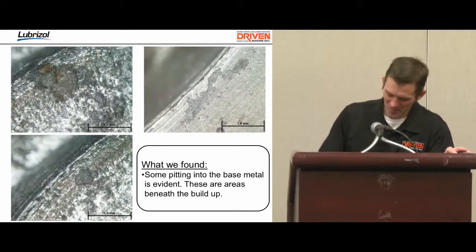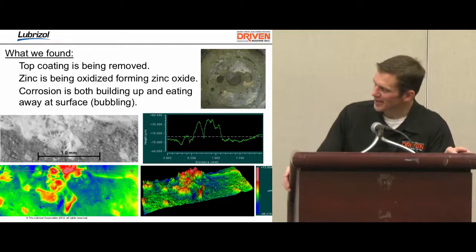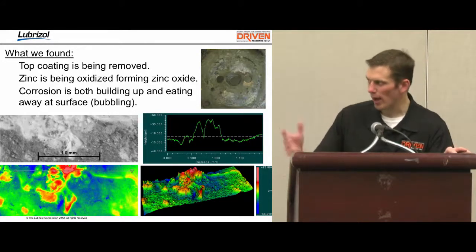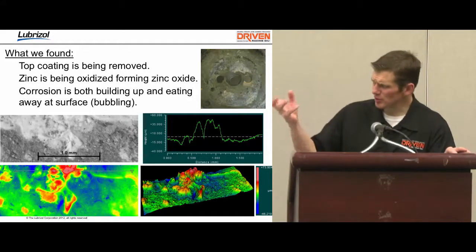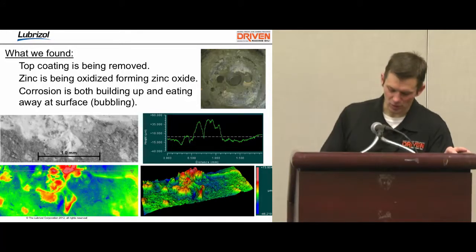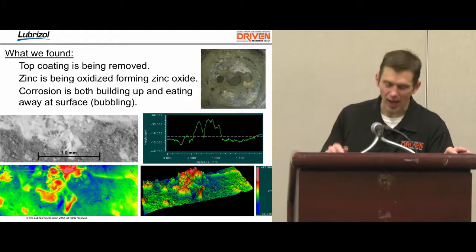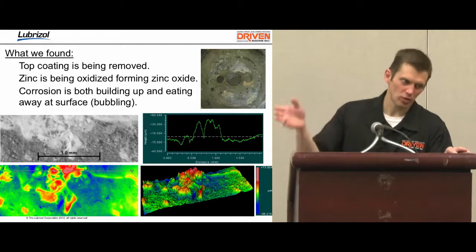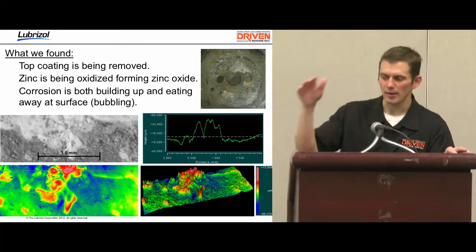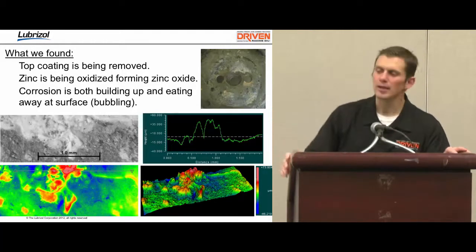Right? A little more high-tech photographs of it, but you get the idea that the corrosion is eating away at the surface. It's just corroding and killing, which is why at some point, if the corrosion goes on long enough, your carburetor is junk and you got to buy a new one. There's just too much material damage to fix it. So this is what the ethanol does to the carburetor, and it's very much a function of time and temperature and concentration. The higher the concentration of the ethanol, the shorter amount of time it's going to take for this to happen. Even at a low concentration, if you have enough time, it will do it.